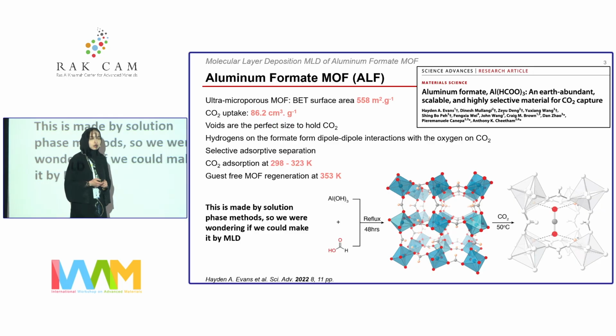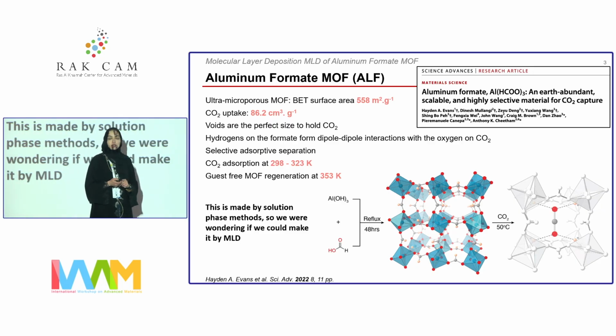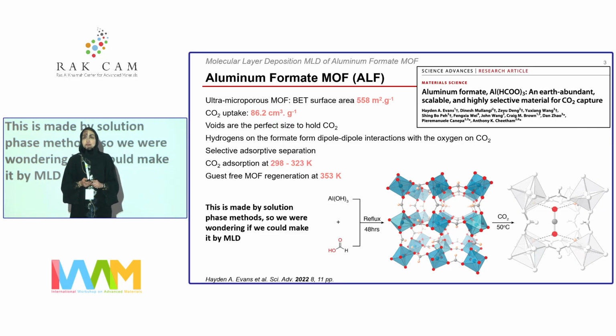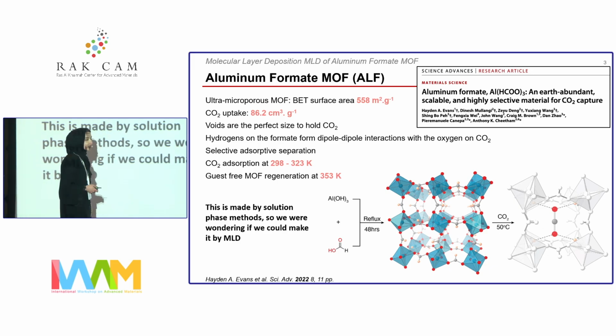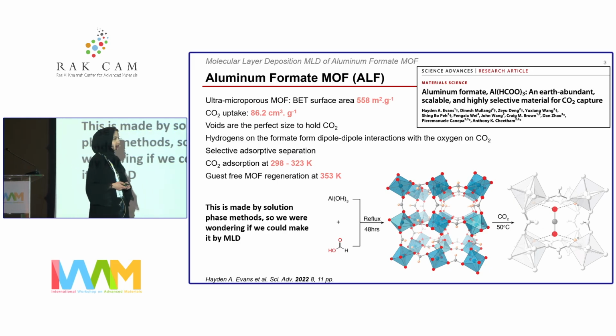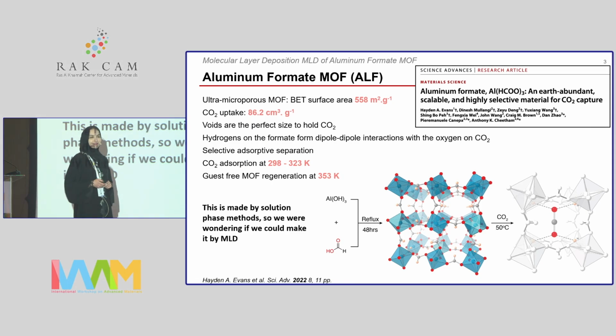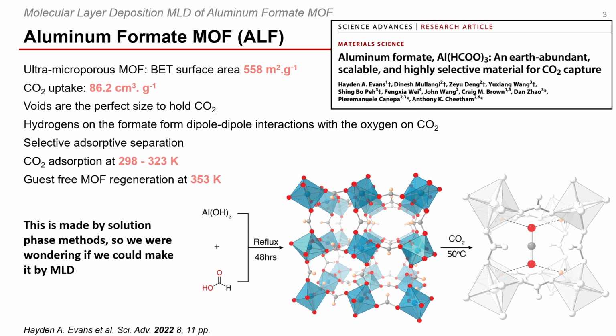We know MOFs are one of the best materials at capturing carbon dioxide, sometimes selectively, like this MOF right there. It's aluminum formate MOF. It was published in 2022 by your group, sir. It was proven that it can capture carbon dioxide selectively through size-selective adsorption, and it also can form hydrogen bonds with carbon dioxide once it's in the pores. The second I saw this MOF published, I went crazy because, look at the building blocks. Formic acid, it can't get smaller than that.